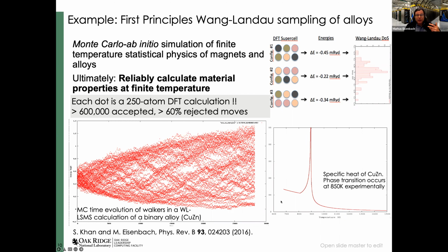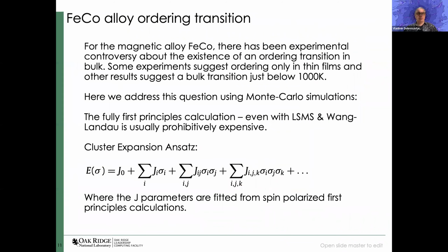correlation. And also we did not drive the simulation to really converge it for all energies, for all temperatures. And you see this in this kink in the specific heat. So basically, all the very low energy states are not yet properly explored. That's why the very low temperature behavior is not quite captured. Of course, this was a very heroic calculation.